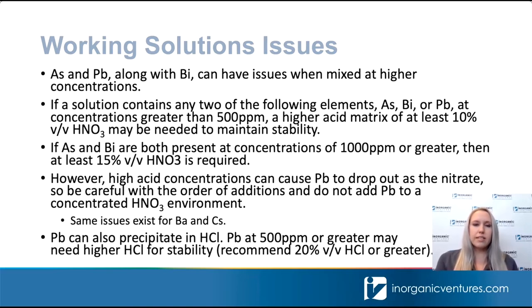Another issue with lead is that it can precipitate with hydrochloric acid. So if you have high lead at about 500 ppm or more, we do recommend increasing the hydrochloric acid content. This just has to do with a stability issue for lead, or a solubility issue, I'm sorry, for lead. So we recommend increasing the hydrochloric acid percent for those to about 20% or possibly even greater. Lead should go back into solution with mixing, so just keep that in mind if you are using hydrochloric acid in your solutions.